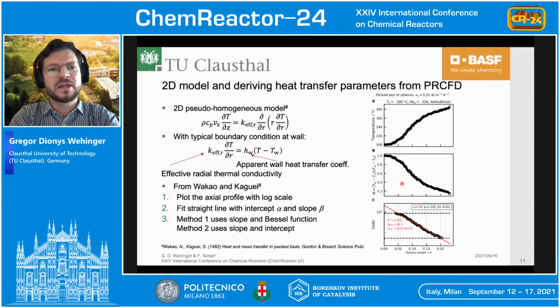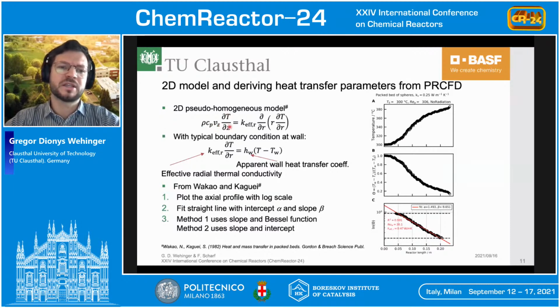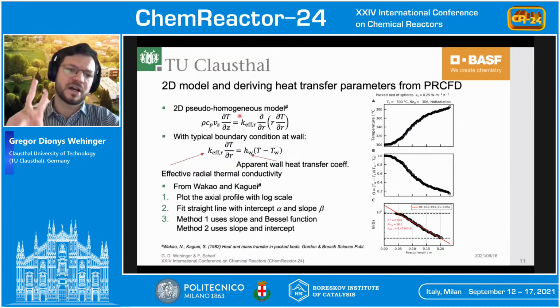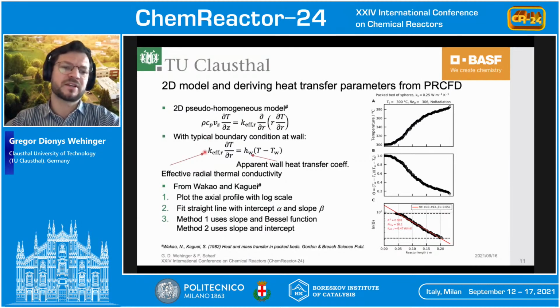So this has to be kept in mind when I go to the next investigation. That means the difference between PRCFD and the 2D modeling approach. So here I give you the equation of this famous 2D pseudo-homogeneous model where we solve for the temperature in axial as well as radial direction with 2 parameters. One is the effective radial thermal conductivity, and the other one is the apparent wall heat transfer coefficient, HW, which then results in a Nusselt wall at this typical boundary condition of the wall.